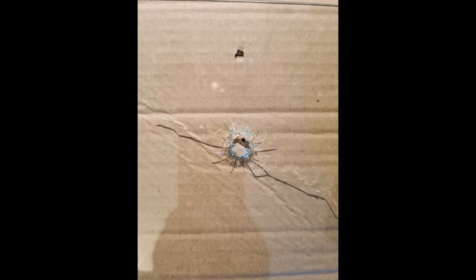You can see here that our brittle material, although stronger, resisted that 6mm plastic pellet. In this case, when it's failed, it has failed considerably more spectacularly. You can see the little hole punched through our softer, more ductile material, and the much larger hole and the rather extensive propagating cracks that have been punched through our stronger material now that its limit has been reached. This means that despite us using our harder and theoretically stronger material, there's now a lot more material inside our ship, a lot more splinters, and potentially a lot more access for more shots to come in of any kind, because a gel pellet, a 6mm plastic BB, whatever, could all fit through that hole.